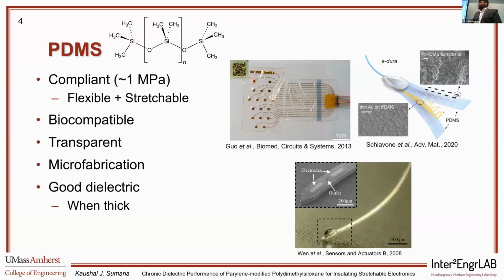So apart from being flexible, it can also be stretchable. It also exhibits some really nice properties like biocompatibility and transparency. PDMS is also manufactured by microfabrication, and we see some examples of neural probes or even wearable interface probes here made with PDMS. PDMS is also known to be a good dielectric, however, with the condition that it's thickness dependent. So very thin PDMS cannot be a good dielectric in certain conditions.